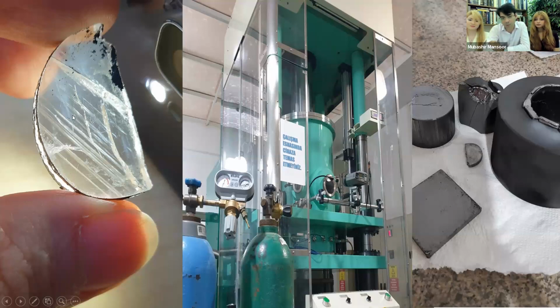This is actually a synthetic. We did it on some synthetic sapphires, and we are still researching on it, so it will be published soon. But what you see here, these straight lines, we could see shear in sapphire. Sapphires sheared so well. By shear, I mean the atoms just displaced so elegantly that we could see them with our naked eye. And that means any process at an atomic scale should be increased or accelerated exponentially if sapphire goes through this sort of a process. And I hope people don't confuse these straight lines with some natural inclusions, but we'll publish this soon. It was a consequence of the pressure that was applied. So that's also an interesting observation that we are showing for the first time here.